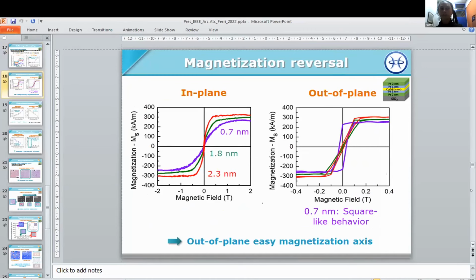Now looking at the magnetic behavior. As a function of the magnetic field, we look at the magnetization reversal of the sample by looking at the in-plane and out-of-plane magnetic curves. We can clearly see that we have an out-of-plane easy magnetization axis, which is what we want. But for the smallest thickness, 0.7 nanometer, we clearly have a different behavior of the out-of-plane magnetic curve, which now has a square-like behavior.